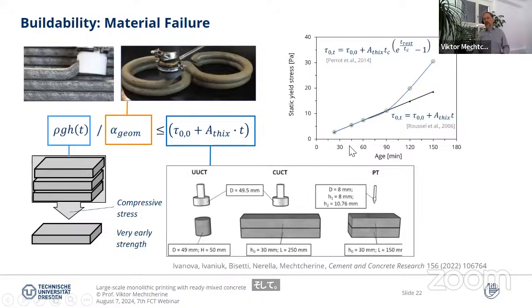But usually we stay here somewhere in this region. And then an important point to mention is that we need to go here to a different type of rheometry than we usually use for characterizing flowable concrete, because in this case the concrete is already not flowable at all, or it flows really very, very slowly under pressure.